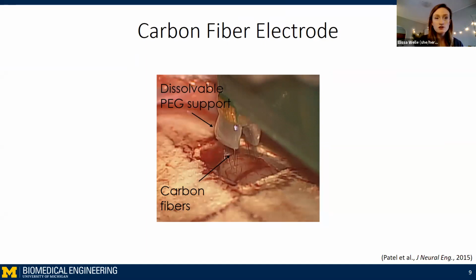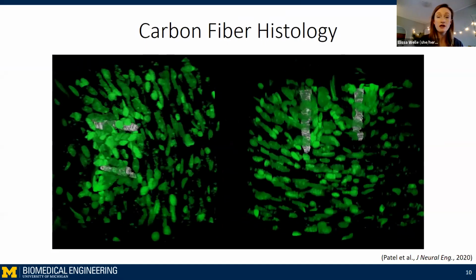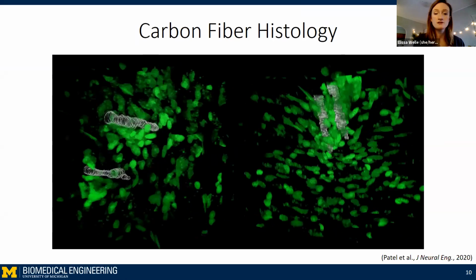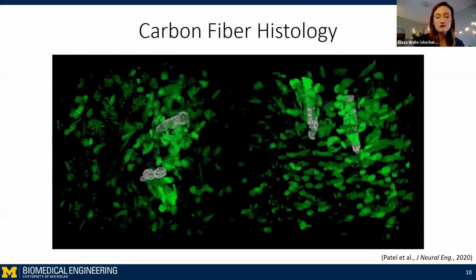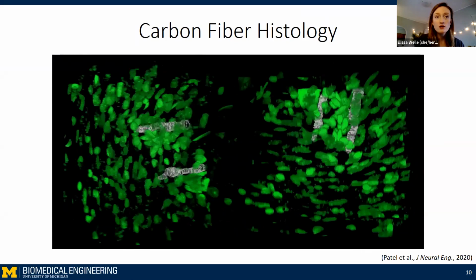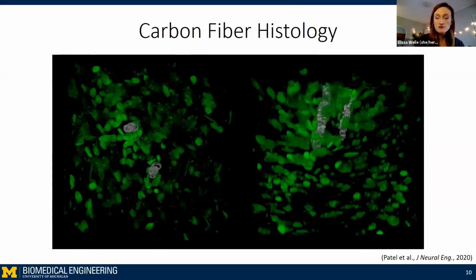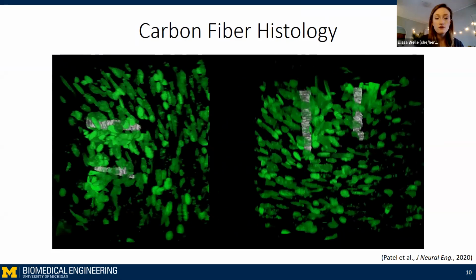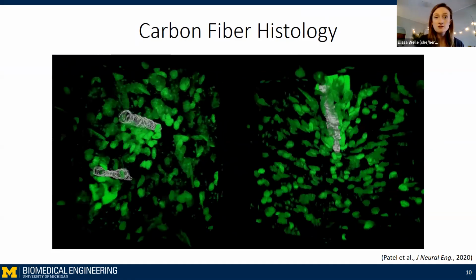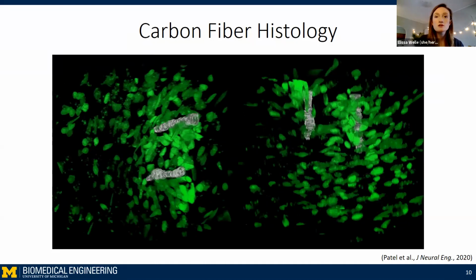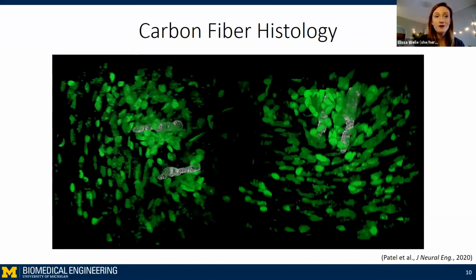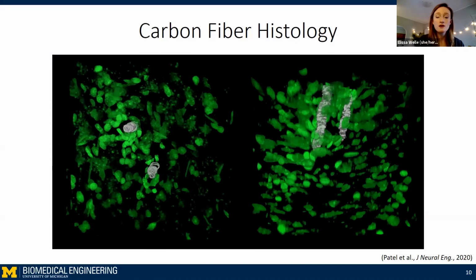And when we reconstruct a 3D image of the tissue around the fibers after they've been implanted for months, this is in rats, we reconstructed it by slice. And this video is showing 2 carbon fiber electrodes traced, and you can see them here in gray from 2 angles, and the neurons are in green. And there's a really dense neuronal population right near the electrodes. You can see neurons cozied right up near the electrode tips, which means that these electrodes are getting many more neurons to record from for future brain-machine interfaces if we were to use these fibers. So despite this very encouraging histology, there's still work to do.